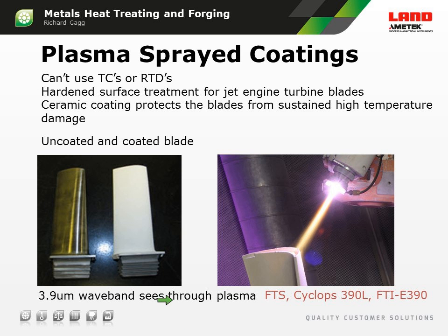Here's another one. In this case, what we see here is a turbine blade, which is used in a jet engine. These turbine blades are coated with a ceramic material, and that ceramic material gives them durability to withstand many, many hours at very high temperatures without affecting the metal beneath. These coatings are applied using a high temperature plasma spray, and in this particular case 3.9 micrometers is used. The FTS or the Cyclops 390L or the FTI-E390 imager can all be used on this application. They will not see the plasma, they will only see the surface temperature of the blade that's actually being coated.